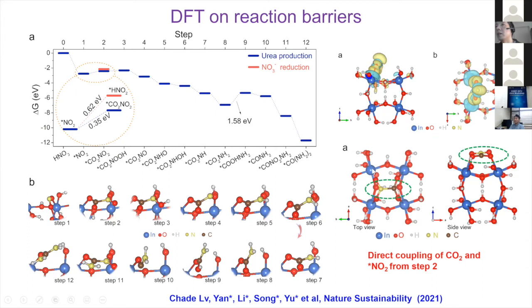And to do this, because this particular catalyst has 4 active surface sites of indium, which is an active surface for the binding of nitrate and also carbon dioxide. Okay, and this 4 active site coordination with proper length allows the nitrogen and carbon to form a linkage under this environment, and that is one of the important processes to promote the carbon nitrogen bonding, and will promote this reaction toward this urea synthesis.